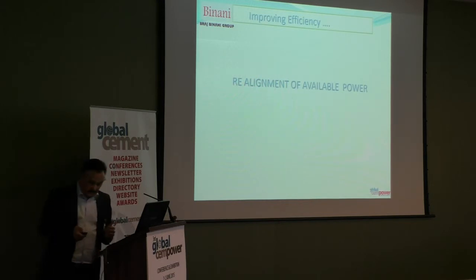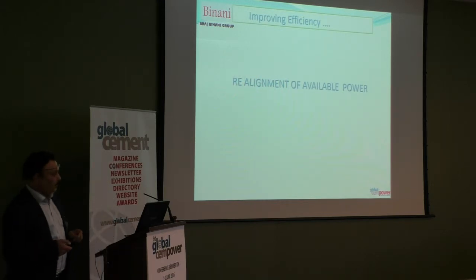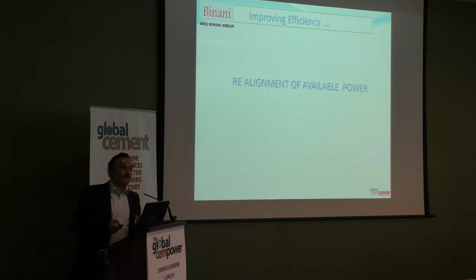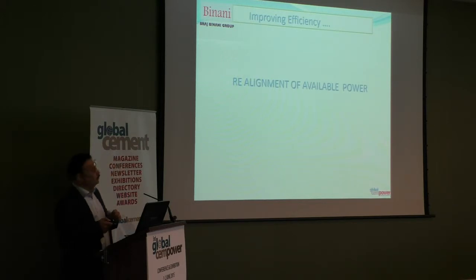So when this problem was thrown at us, there was a situation. We invested almost about $25 million in that Chinese mill. And in 2012, up till the middle of 2013, we were staring at this cost as a sunk cost. There was no solution available to us. And the reason was, now you have seen that the power was available to all three mills. But the last mill, where you have a split, you have 3 megawatt and you have 2 megawatt. The major problem is the main drive for line 3 actually required 3.8 megawatt. So if you do not have available power, you can't run it.